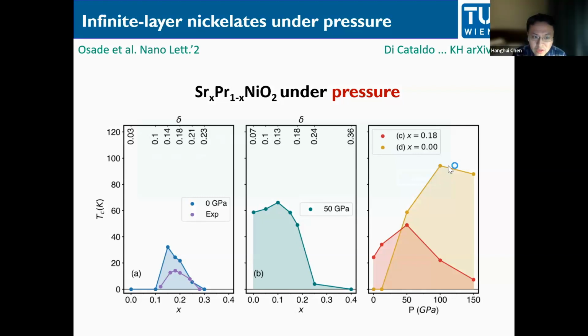Okay, but when you show this TC, when you calculate all this TC, you still use the single orbital model. It is still in the single orbital model, and even though the pocket is larger, and it's the gamma pocket, we did the single orbital calculation. But actually, it's a result of the fully 5 + 5 DFT plus DMFT calculation. So you should have this much of doping into your x squared minus y squared orbital, and in DFT plus DMFT, there's no z squared orbital yet either. And these pockets remain weakly correlated.